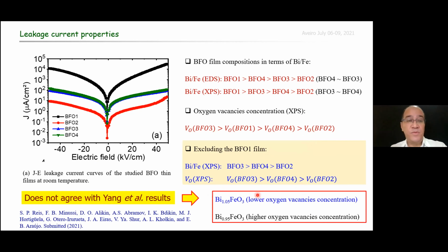Okay, this result does not agree with the Yang et al. results shown previously. They observed or concluded exactly the opposite. Their films with bismuth in excess result in lower oxygen vacancy concentrations, while bismuth deficient film produces higher oxygen vacancy concentrations.